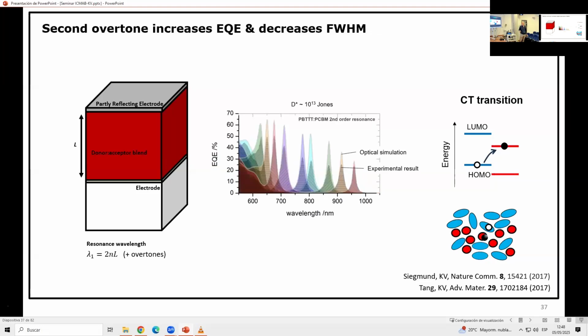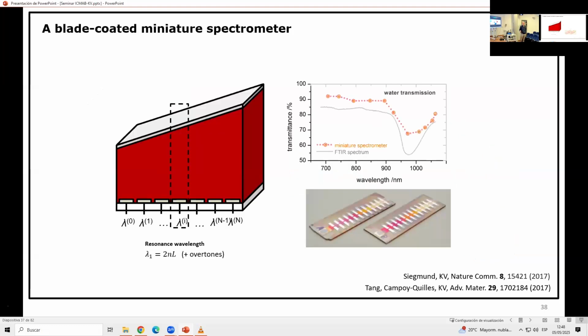And this is how, together with Mariano, we measured this. We made the spectrometer. Okay, yeah, if you make a double stack, you get the double resonance, and you can make smaller peaks and so on. This is also what you would expect with the optical simulation. So something where it didn't look like it absorbed anything, we all of a sudden have 25% conversion yield, which is not 100, but it's nice. So in this way, with one material blend, you just make a thickness wedge, and that's what they did here already a long time ago. You can make the spectrometer then. That's how it was made.